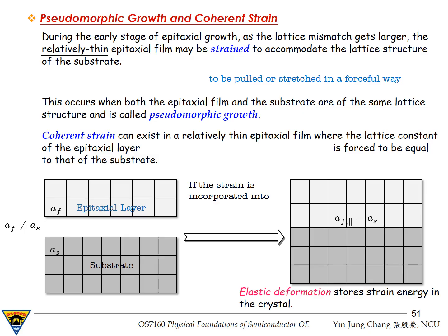Because the film is forced to match the substrate spacing, the lattice inside the film becomes strained. That is to say, they are pulled, stretched, or compressed in a forceful way. This strain is incorporated into the crystal coherently, meaning the atomic rows remain continuous across the interface, as you can see here. So in a coherently strained structure, the interface remains perfectly ordered, without dislocations or broken lattice continuity.